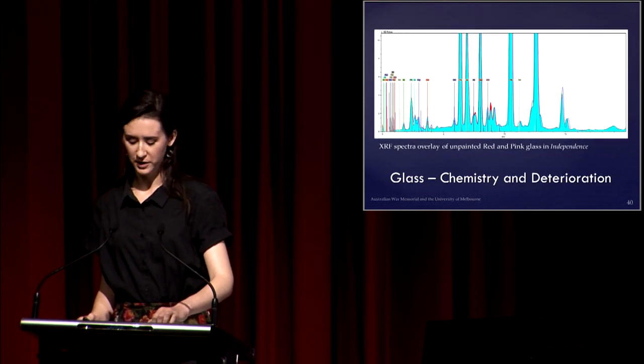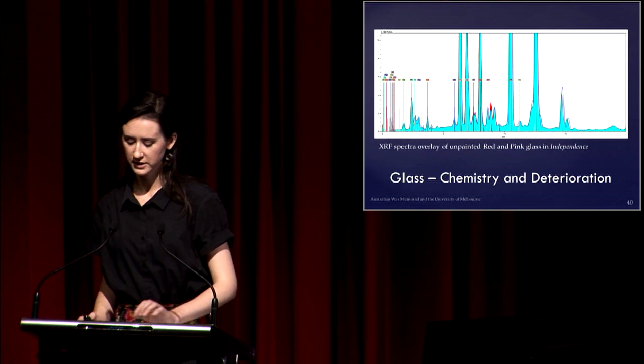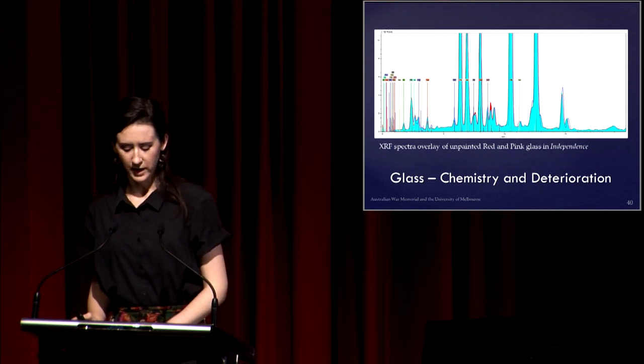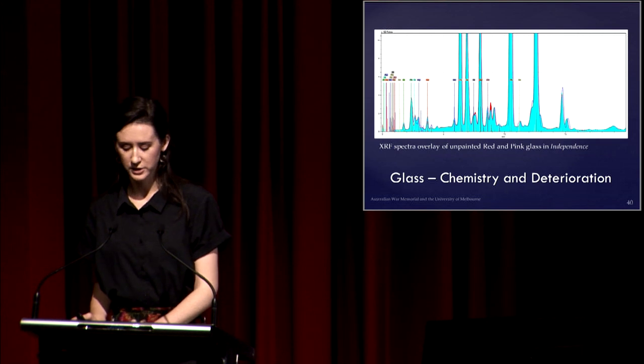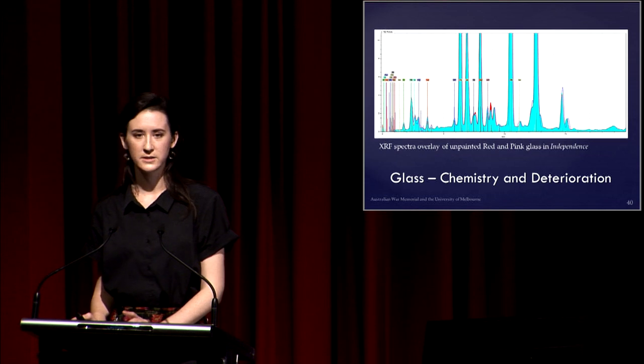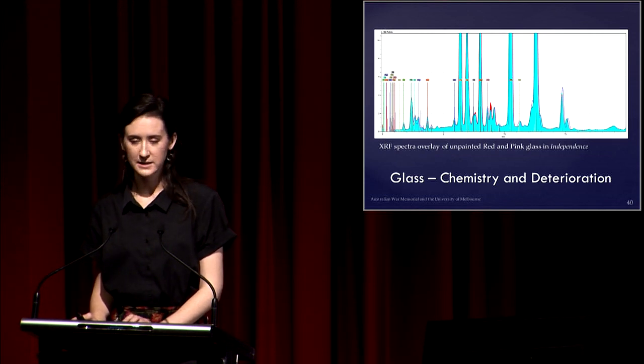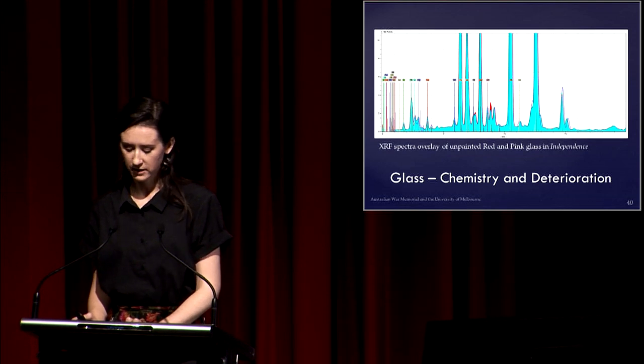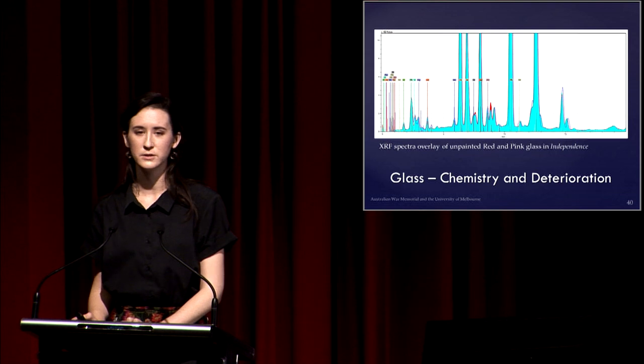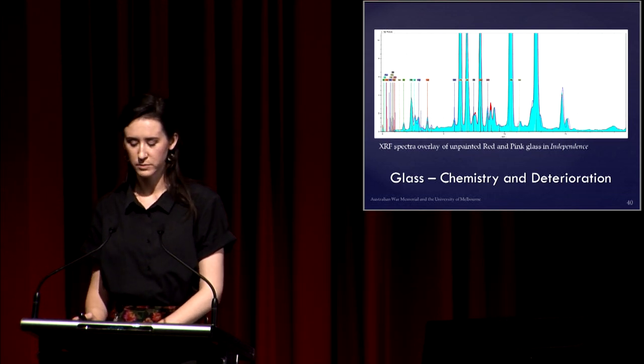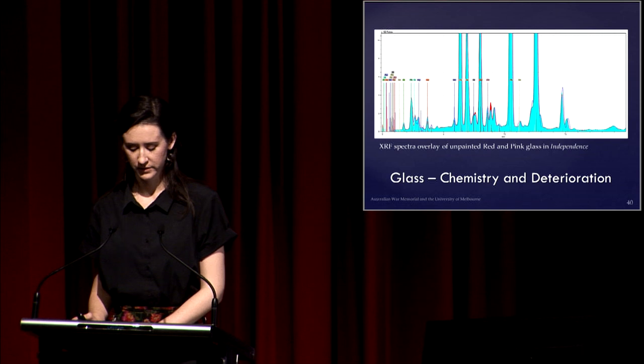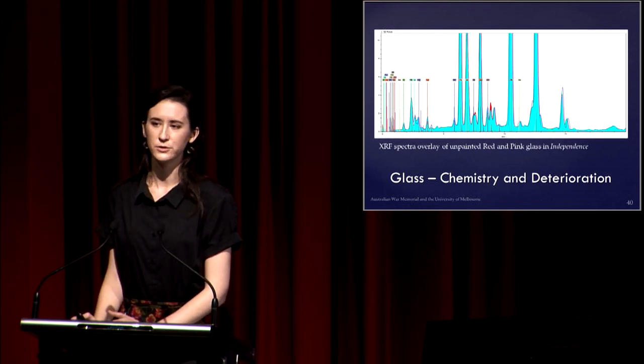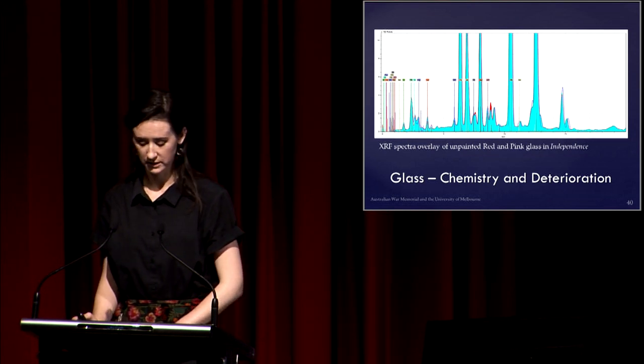Not all of the glass in the windows is exposed to the elements, as it's coated in enamel in most areas. We analysed the composition of the exposed glass, which indicated the presence of silica and metal oxides that produce colour as well as stabilise the network. SEM EDX analysis completed by Bassett also indicated that the potassium levels were much higher than sodium, which means that the glass will be more vulnerable to water damage. With the right combination of water and pollutants, this process may still take 50 to 100 years to begin and start to cause significant damage.